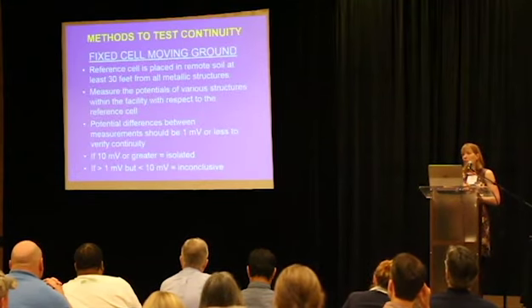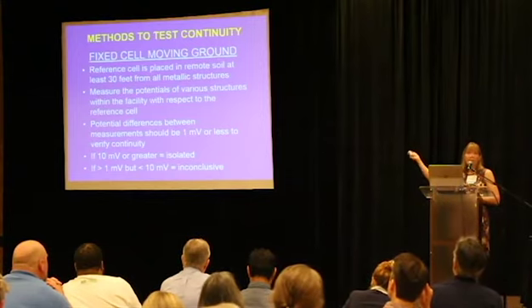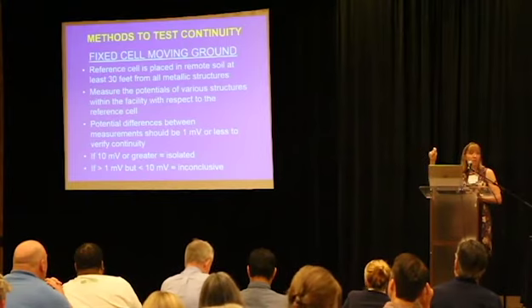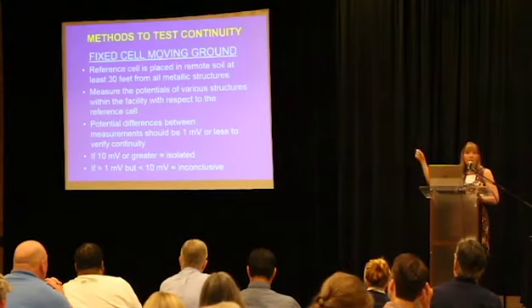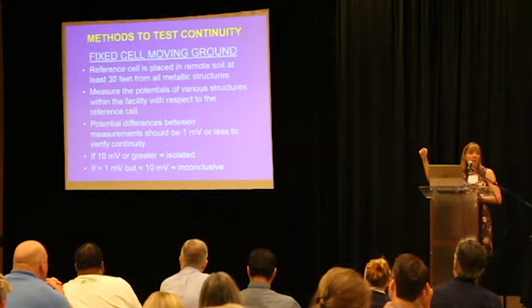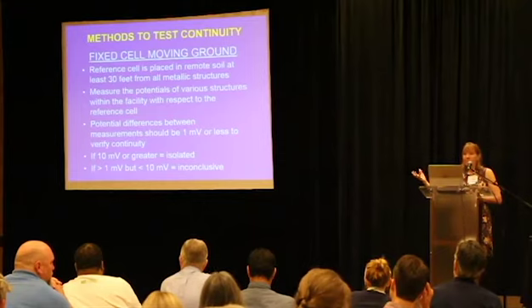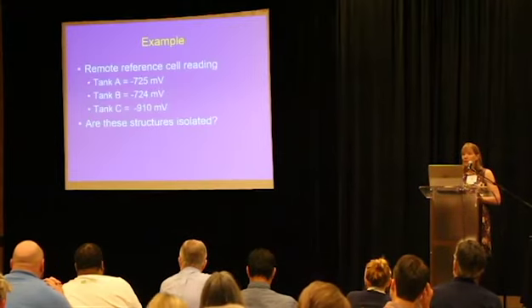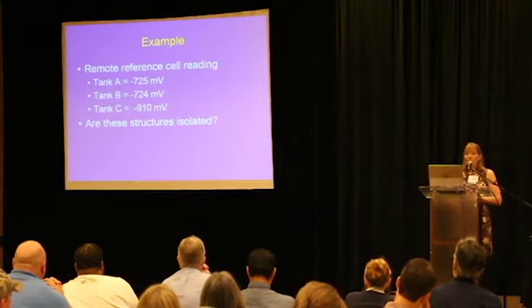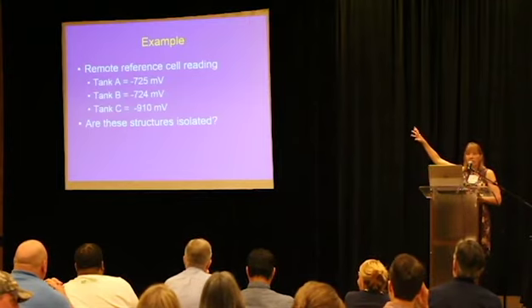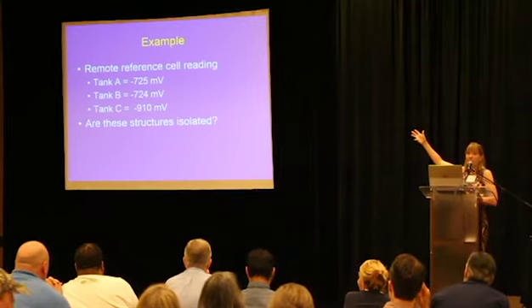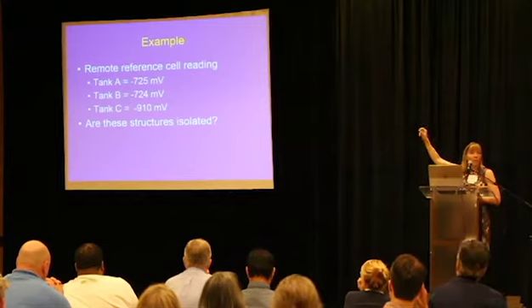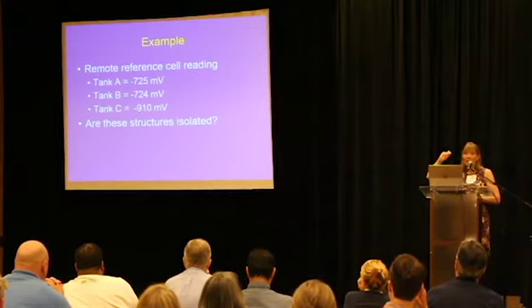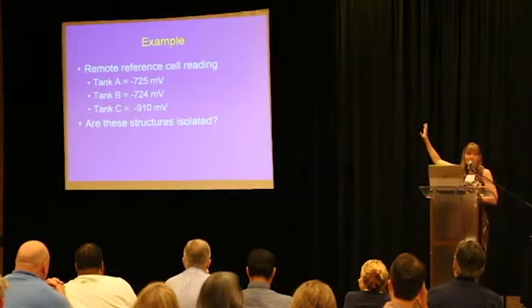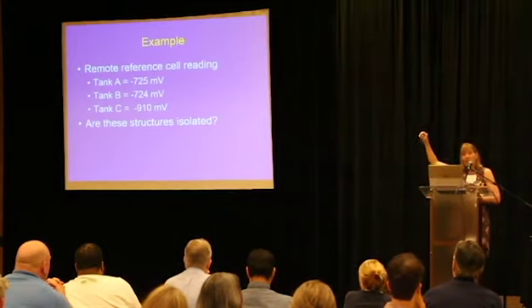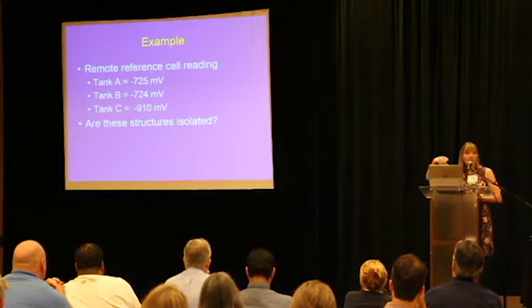One's called fixed cell moving ground. And a fixed cell moving ground is simply taking remote readings on any and all structures that you'd like to check to see if they're continuous. If those readings are the same, the structure is continuous. If they're 10 millivolts or more apart, they're isolated. So as an example, you've got 3 tanks. You've taken remote readings on all of them. One's negative 725, one's negative 724, one's negative 910. The first 2 are only 1 millivolt apart. That's definitely less than 10. Even if you're not a math whiz, that's less than 10. And so those two structures are continuous, but structure B is isolated from structure C, as well as A being isolated from C.